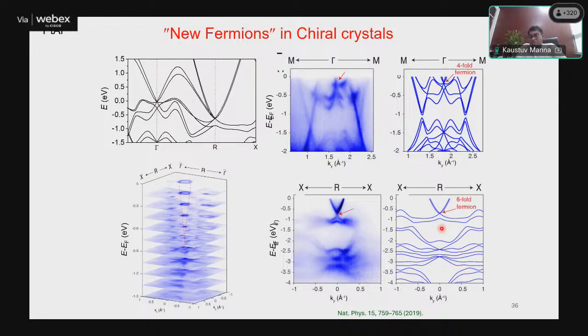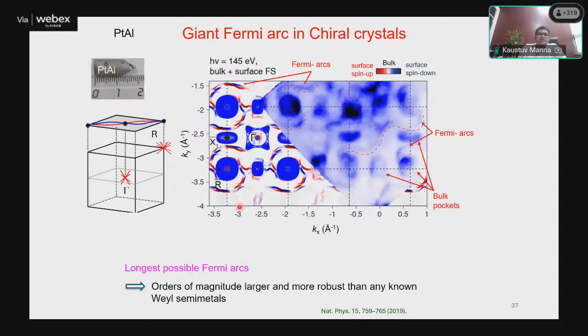Now, if these band crossings are Weyl points, then what is the experimental proof? What you have to do is energy dependent surface state measurements, and if you can find a surface state connecting from the gamma point to the R point, then we know that this surface state is the Fermi arc. So this is our surface state experiment, where we can see that this is the Fermi arc expanding the entire Brillouin zone.